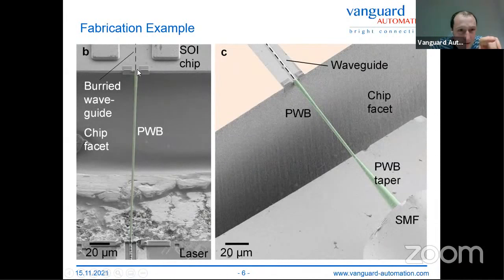And you can see, if you look carefully, it's compensating some lateral misalignment, which would otherwise lead to, well, incredibly high coupling loss. And with this, we can typically do, let's say, 2 dB, that's a very reasonable value. We can go lower in some situations. So the performance is really attractive, I believe.